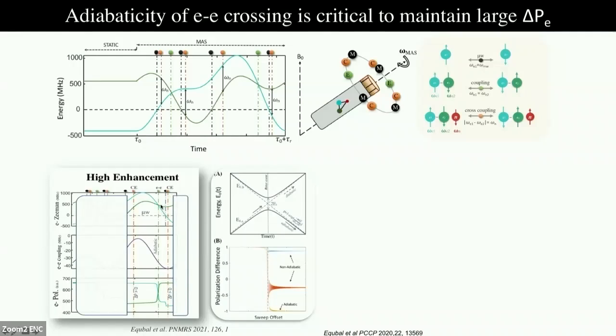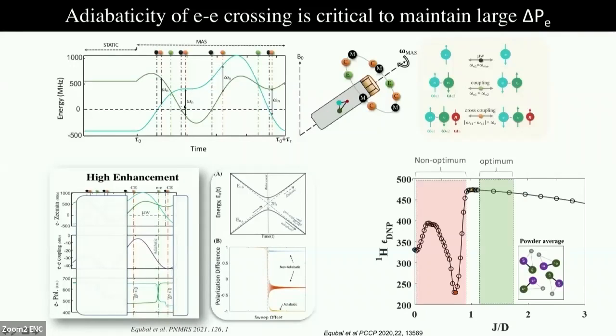So I'm trying to show here a picture of what the crossing should be. If we have, say, this crossing here, the coupling has to be large in order for the transfer, or the exchange of polarization, to be adiabatic. If it is strong coupling, we'll have a 100% swap of polarization, but if it is weak coupling, then we'll have a diabatic transition where the polarization difference would be smaller. So in order to have a good cross effect DNP, we need to have a ratio of J and dipolar coupling which is above 1, so that we don't hit this non-adiabatic condition.